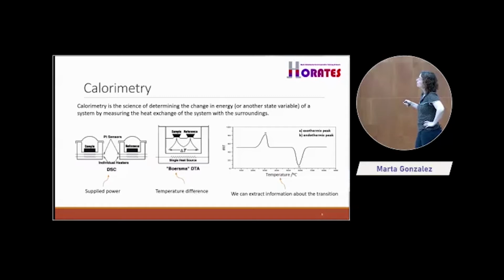What we do is to have a reference and a sample, the one that we want to measure. And at any moment we control the temperature of the system. These are supposed to be sensors. We control the temperature of the system, and what we do is to provide power so these two samples follow a certain temperature program. Let's say we want to heat it up at 10 Kelvin per minute, whatever. We heat it up at 10 Kelvin per minute, and I have to provide certain power depending on the specific heat of the system, okay?